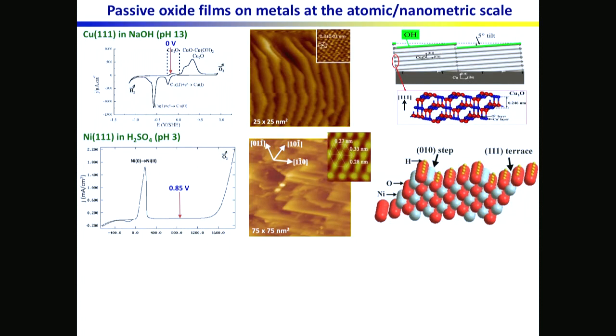And actually, this is the superstructure of the oxide surface. And that's interesting because this oxide is also covered by a layer of hydroxides. And I would like to state there that normally nickel oxide does not grow in the 1-1-1 direction, which is, however, shown by this image, because nickel oxide is a so-called polar oxide.